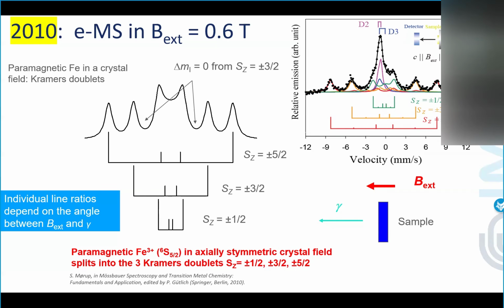No trace of long-range ordering in the extremely dilute case. Unusually long relaxation rate, of course. With Mössbauer, you cannot directly measure spin-lattice or spin-spin relaxation, but we did something that I will show in the next slide: by judging the temperature dependence of the average line width, you can somehow extract the spin relaxation. And then by doing a temperature dependence, you can identify whether there is more spin-lattice or spin-spin relaxation.